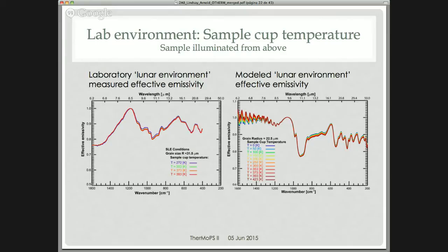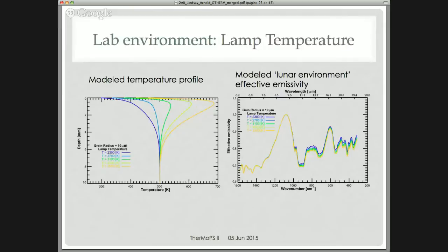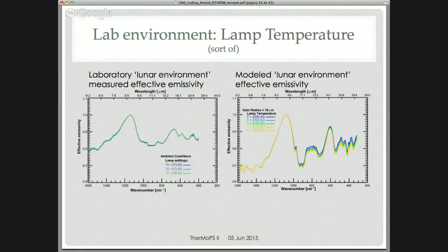All right, the next thing I tested is different lamp settings, and the way that we tune this is a little bit different in the model than in the lab. So in the model, I just took a variety of lamp temperatures that vary quite a lot, a few hundred Kelvin. And so this is the model temperature gradient here, the modeled emissivity spectrum. And now here's our actual measured lunar environment effective emissivity.